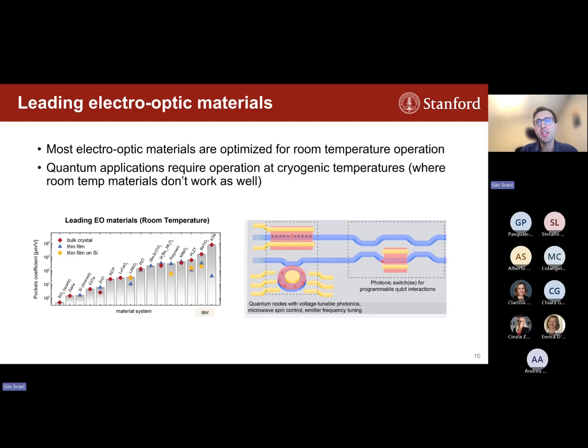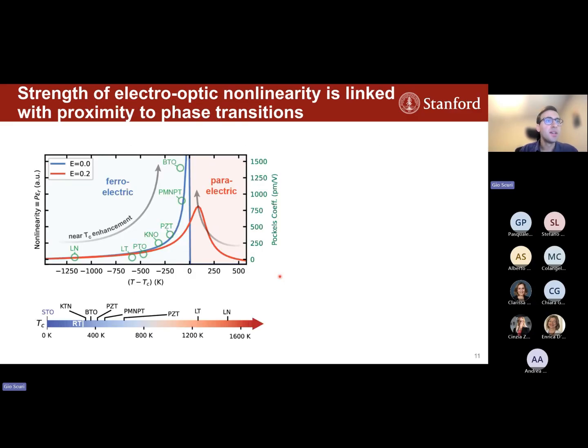But one challenge is that for many of these materials, or actually most of these materials, their performance actually degrades as you go to cryogenic temperatures, which is where you want these materials to operate, because you need them to be integrated into nanophotonic circuits, where you also have spin qubits that often require these cold temperatures to have enhanced coherences for your quantum applications. In a way, this is because you're basically going from systems that are close to phase transitions to systems that are farther and farther away from phase transitions. And it turns out that the proximity to phase transition actually gives you a lot of information about how strong the nonlinearity is in these systems.